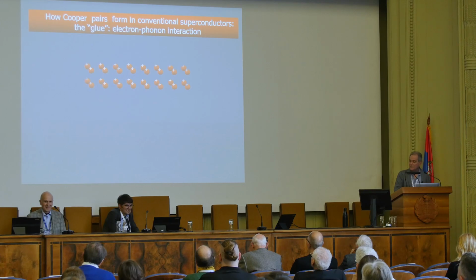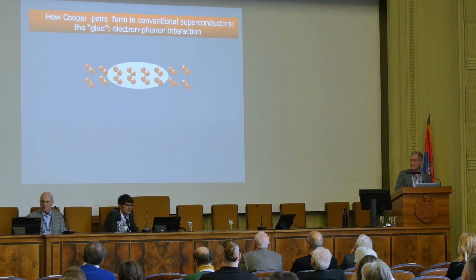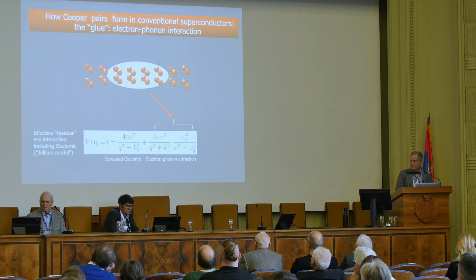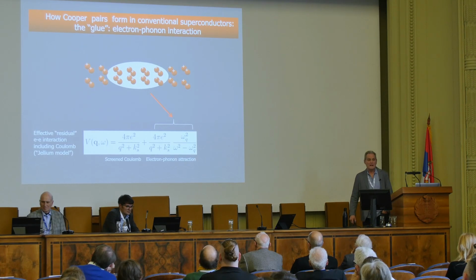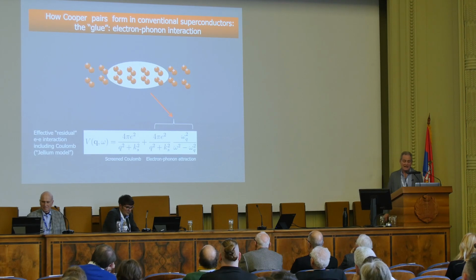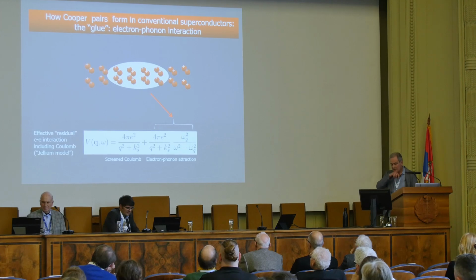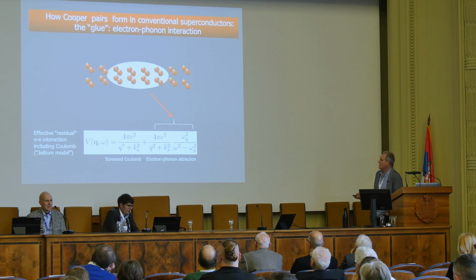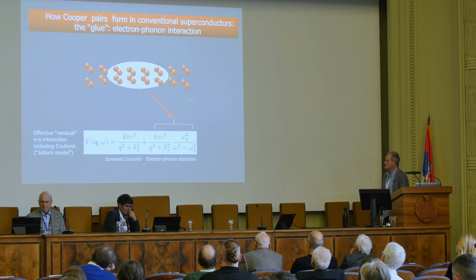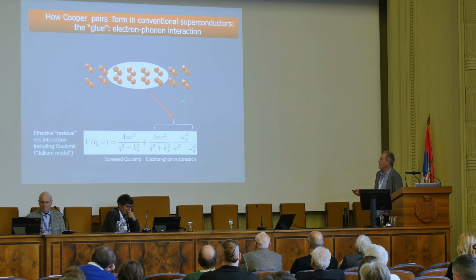So the slightly more accurate picture is that you have an atomic lattice where the ions are positively charged. An electron comes in with some momentum. It polarizes the lattice. It's fast, and the ions react very slowly, so that excess charge builds up and it stays for a while. It's around when the second electron comes along with opposite momentum, and it can take advantage of that excess positive charge to lower its energy. And if you do a simple calculation for an electron gas with a neutralizing positive background charge, that's called the Jellium model, you find that there's a screened Coulomb part of the interaction and an electron-phonon interaction which has some dynamics associated with the dynamics of the electrons and the fast electrons and the slow ions in this picture.